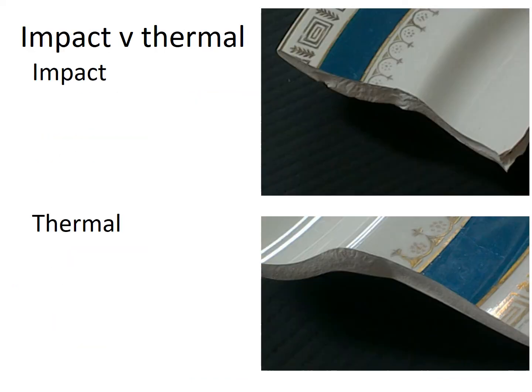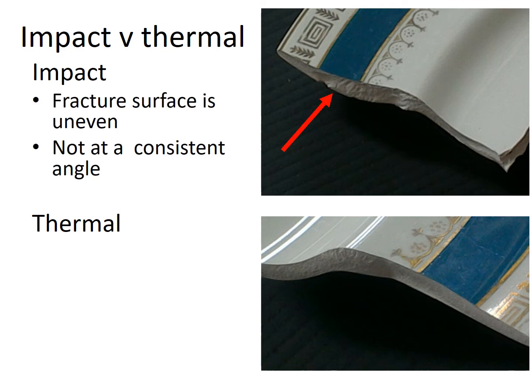So now if we look much more closely at the fracture surfaces of our sample of broken plates, we'll be able to see differences between impact, thermal and bending fractures. The fracture surface of sherds from impact breaks is often rough. At points along the fracture, one side of the fracture will have a slight overhanging lip, with the opposing side having a slight hollow or negative. The angle of the fracture surface is not always at 90 degrees to the surface of the plate and varies along the line of the crack.